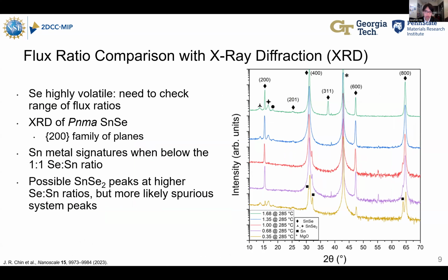So, flux ratio. When we are growing these films, if we were to deposit one-to-one stoichiometric tin and selenium sources, like in the red, we would end up getting some excess of tin. One of the issues is that selenium is a highly volatile material. It's going to readily desorb from the substrate as soon as it arrives. So we need to oversupply our selenium.